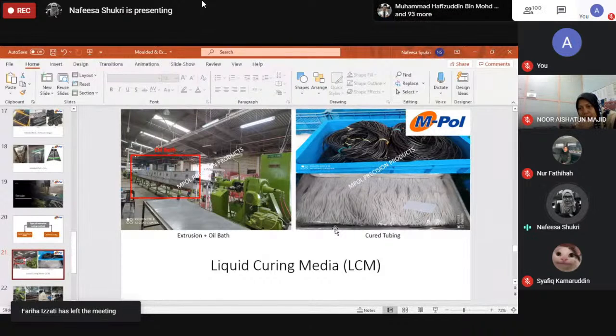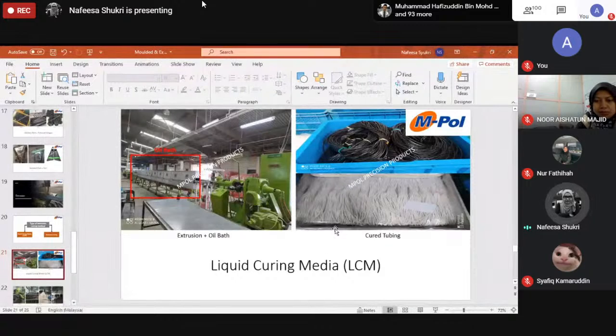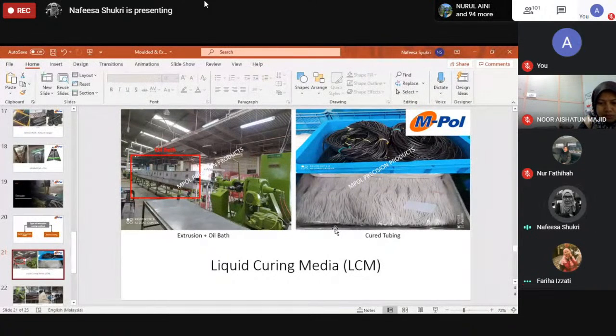But the disadvantage of LCM is that we can cure only if the product is not too thick and not too big, because we have only a 6 meter oil bath. If the product is too thick or too big, the rubber product is uncured at the end of this process. So it depends on the size of the rubber tubing whether it is suitable for this oil bath. Not all rubber tubing is suitable to be used in an oil bath. It depends on the rubber thickness and also rubber size. Also, as you can see here, the rubber tubing is not too big, so that it can go and cure in the oil bath.